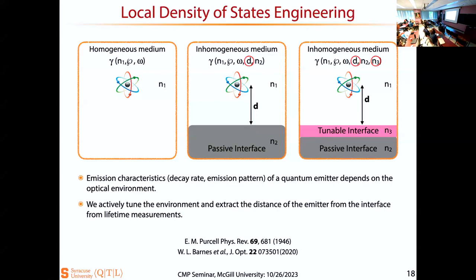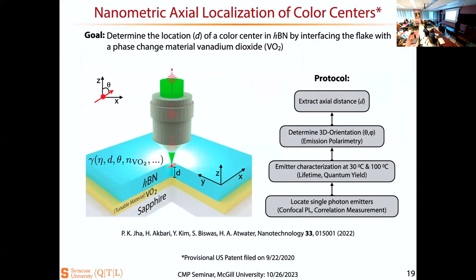But then, to really extract both the dipole moment, because you have two parameters, the dipole orientation and the distance, we need another degree of freedom. That extra degree of freedom was provided by an interface whose refractive index we can change. Combining these two, we were able to really localize where these color centers are. And here is that material. This goes back to the question I was asking. The boron nitride example, the color centers we don't know. Using AFM, it was around 3.5 nanometers.